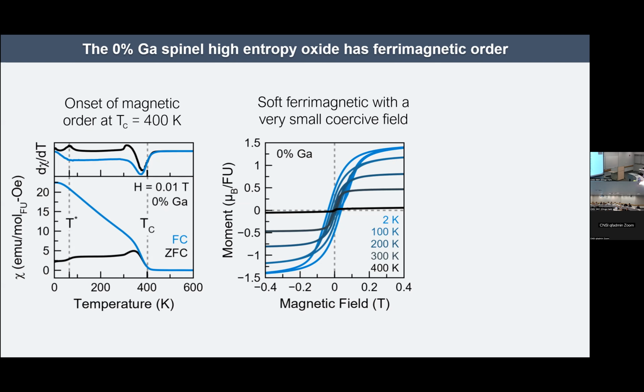That's very small for 3D transition metal local moments. The moments that we would expect to see for many of these elements would exceed 5 Bohr magnetons. And so there's no way that a long-range ordered state involving all of those elements could produce a saturated moment this small, meaning that there has to be some moment cancellation. So this limits us to looking at ferrimagnetic order. There's some partial sublattice cancellation at the moment.